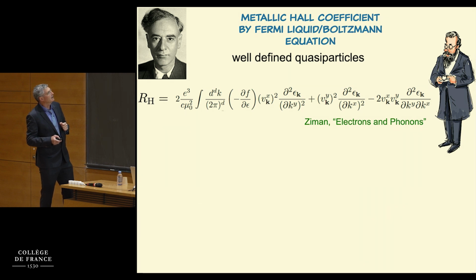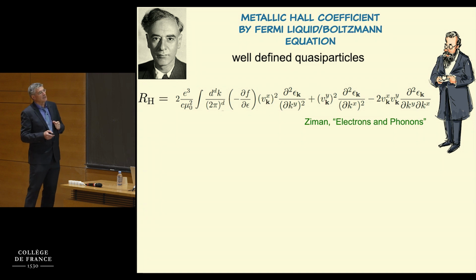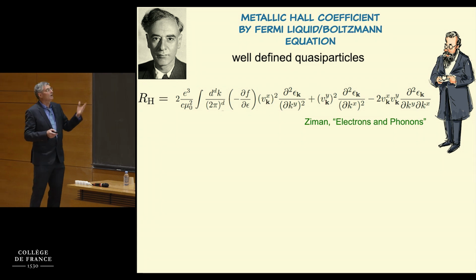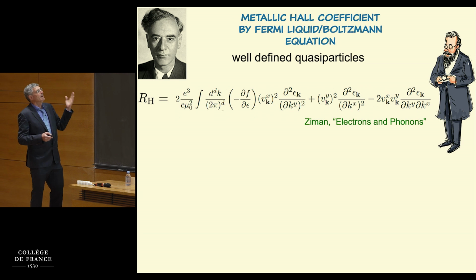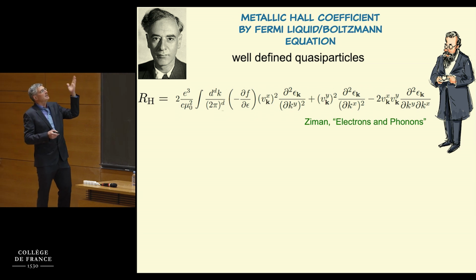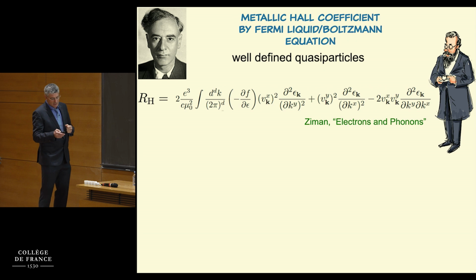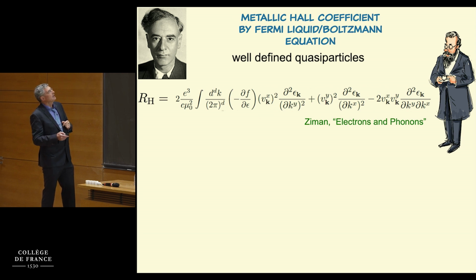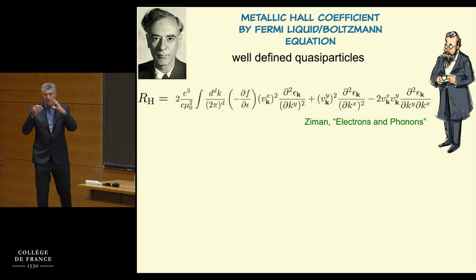Okay, so if one looks at expressions for the Hall resistivity from the Boltzmann equation and band structure, you get this formula. It's in the old textbooks of transport theory. This formula for the Hall coefficient is actually an equilibrium formula. It is derived in the approximation that the lifetime doesn't depend on the position on the Fermi surface, but it's totally a geometric function that only cares about the curvature of the Fermi surface.